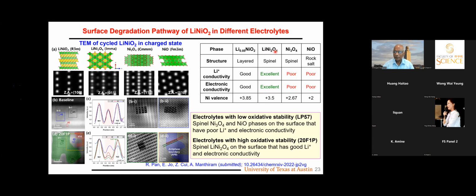In contrast, if you have the conventional electrolyte, we form Ni3O4 spinel and NiO. Or in other words, in the case of good electrolytes, the cathode surface is not reduced very much. It stays around 3.5 LiNi2O4. That's a good 3-dimensional spinel structure, with excellent electronic conductivity and excellent lithium-ion conductivity. So it does not cause much problem.